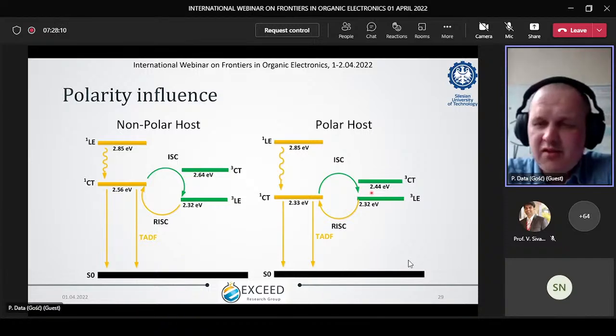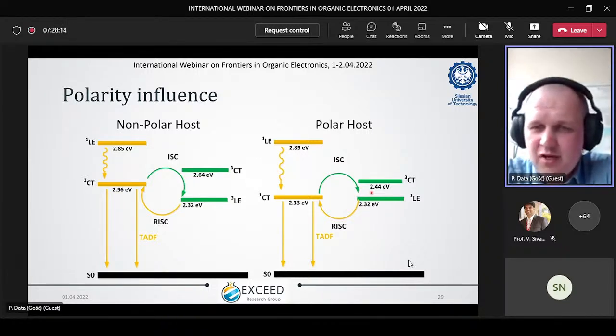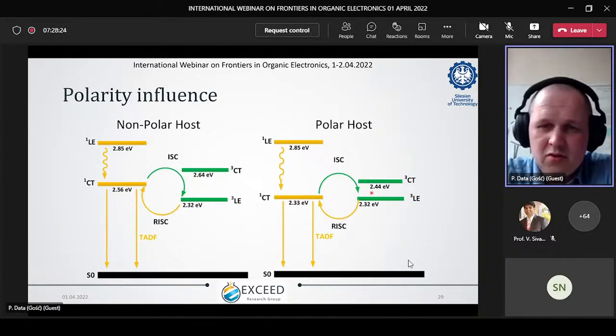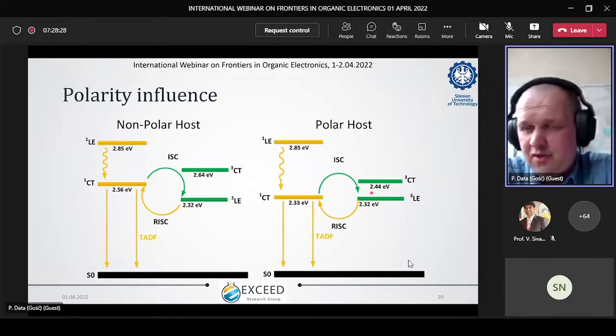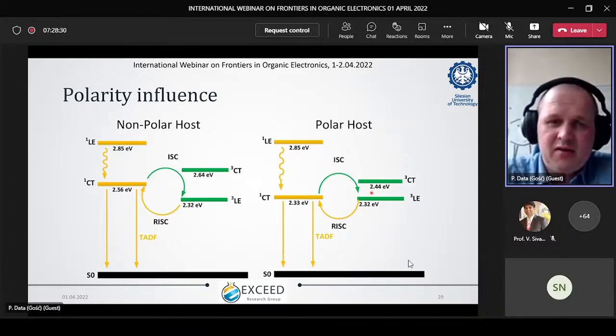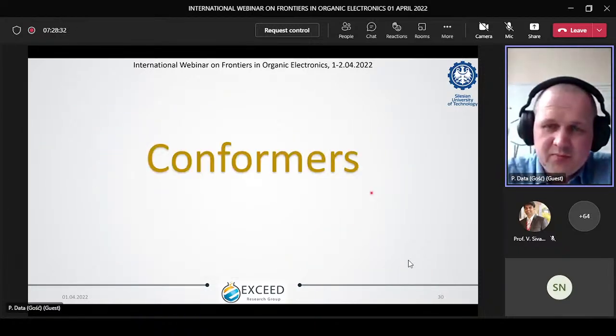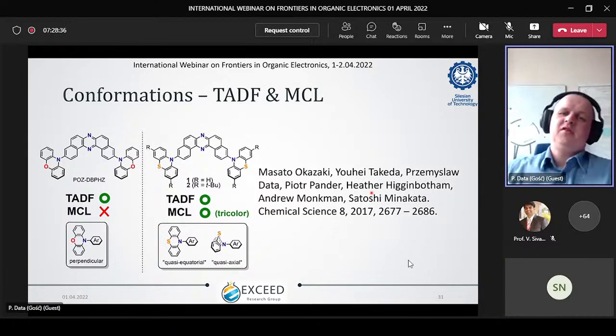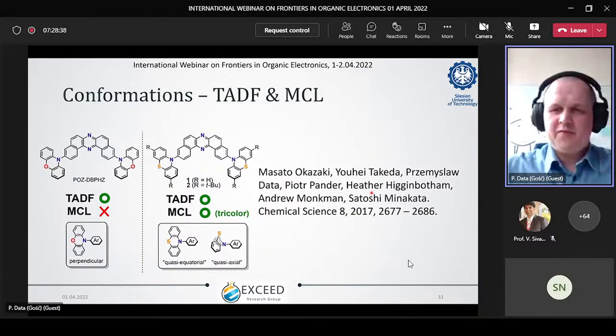Because in some cases, especially if you are analyzing in the solvent and you are saying you have TADF there, it doesn't mean you will have TADF in the OLEDs. And the other way around, you may not have TADF in your solvent, in toluene or THF, when you are doing the screening, but you will have it in the OLEDs. That's why host matters.